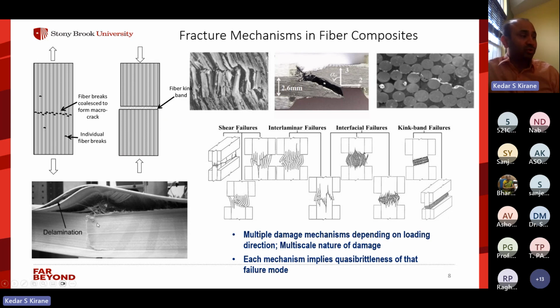There is also, of course, the possibility that overall layers can separate within a laminate, so that is called delamination. And there can be transverse tension, which causes cracks to grow like this, as shown on the top. This is a cross-sectional view of the composite. There is transverse compression, which causes an inclined shear crack. And then under compression, there are actually many modes possible, like shear failures, interfacial failures, fiber crushing, interlaminar failures, and kink band failures. So this fiber kink band is one of the most commonly observed failure modes under compression.